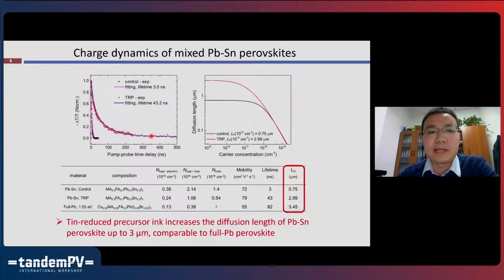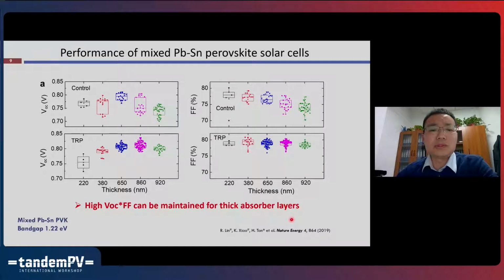This gives us a much longer diffusion length in the perovskite film. The diffusion length can be improved from below 1 micrometer for the control sample to almost 3 micrometers in the target sample. This diffusion length of the narrow band gap perovskite material is almost comparable to very high quality full lead-based perovskite films that give us efficiency of about 23%. Due to the increase of the diffusion length, we can simply think that we can further increase the thickness of the absorber layer.